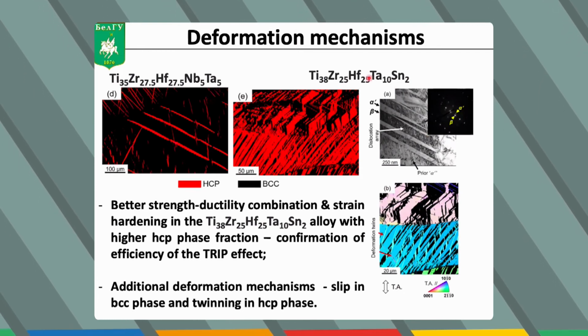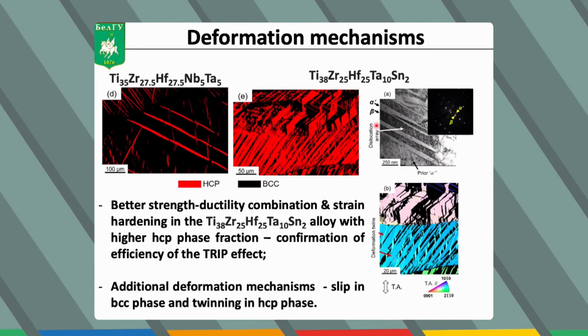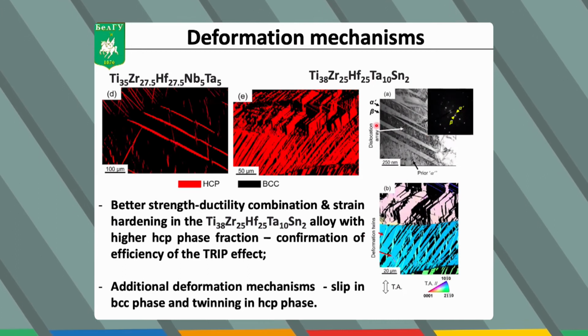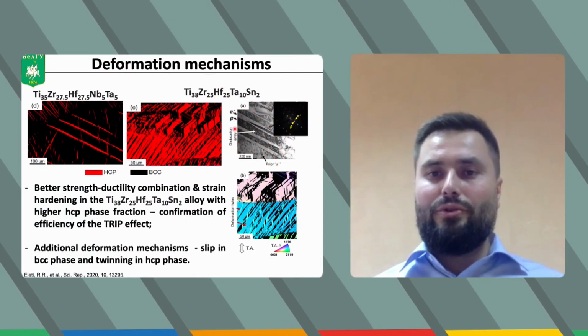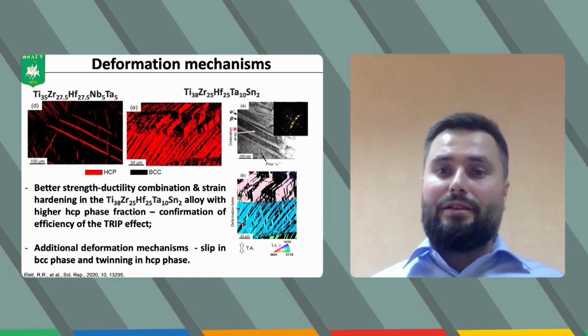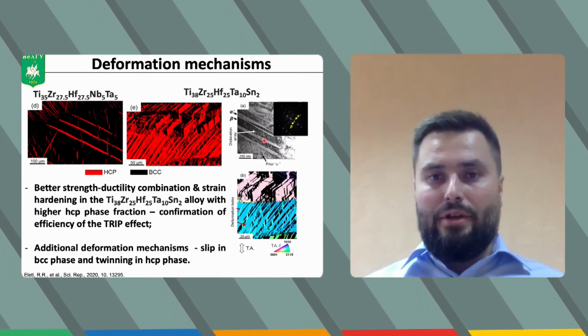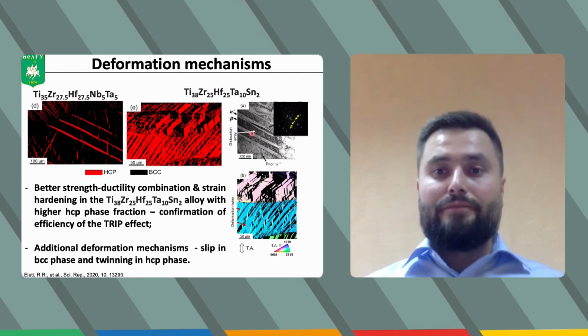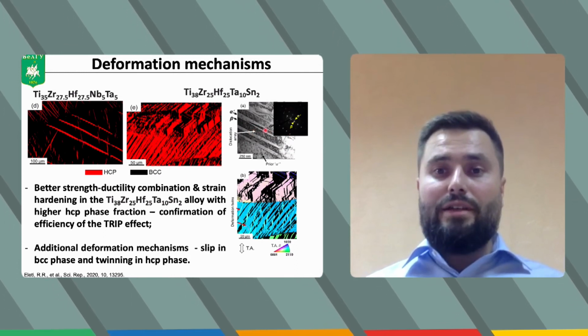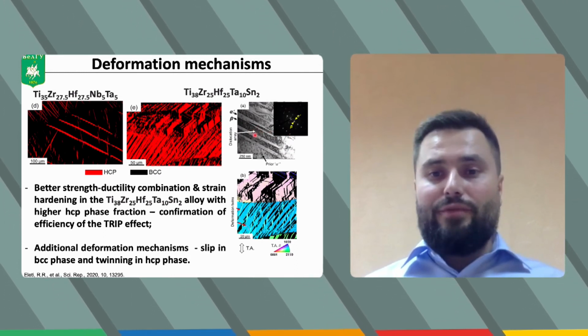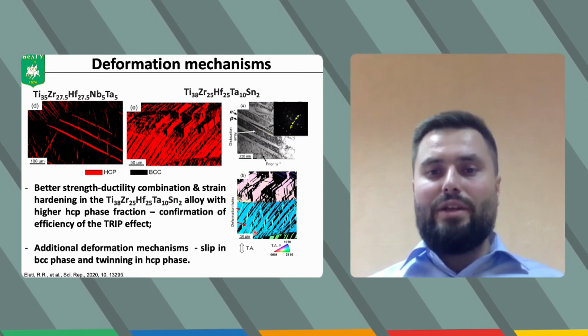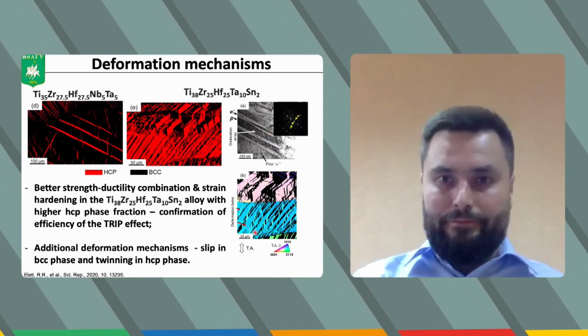But the picture is not that simple. There are other deformation mechanisms that also contribute to the improved strain hardening behavior of the alloy. For example, the dislocation slip in the BCC phase or deformation twinning in the HCP phase.